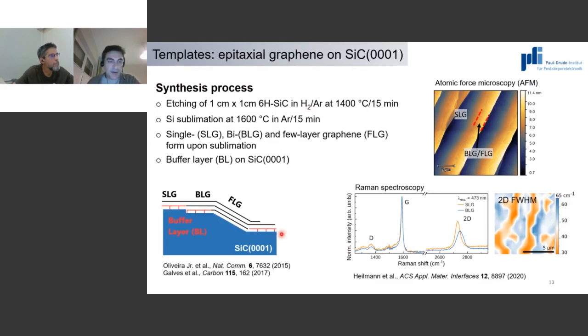the so-called buffer layer, which you can think of as a graphene layer which is partially bonded to the silicon carbide substrate. So you have some sp3 hybridization. It's not purely sp2, but you also have about 30%. This has been demonstrated by other groups, that 30% of the bonding is sp3. That means it's bonded to the substrate. But nevertheless, it's an epitaxially aligned graphene surface that you get, so that is perfect for van der Waals epitaxy studies.